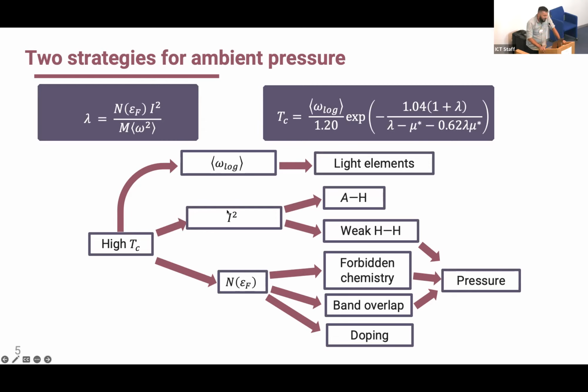The large electron-phonon matrix element, as we saw, we can get it in sulfur hydride, for example, so with one element that is not hydrogen bonded to hydrogen, or we can get it from a hydrogen-hydrogen interaction. In the second case, we will need pressure. Now, for the density of states, we can go through multiple pathways. We can have forbidden chemistry, so we can have a composition that we would not expect to obtain at room pressure,